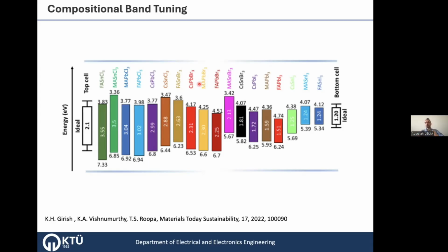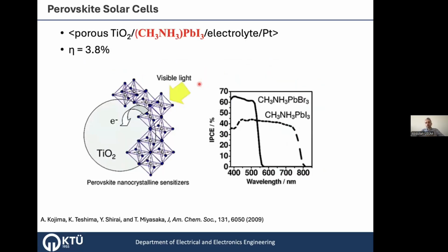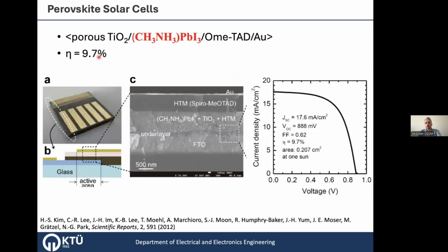So these are the perovskite basics, and the first use of perovskite in a solar cell structure was back in 2009, using perovskite as a sensitizer in dye-sensitized solar cells. But at that time, it was a very new material and it degraded very fast in the electrolyte. That's why only 3.8% efficiency was reported. After 3 years, a perovskite structure very similar to the one I showed, with spiro-MeOTAD as the hole transfer material, as one of the first solid-state solar cell structures with perovskite, was formed with an efficiency of 9.7%.